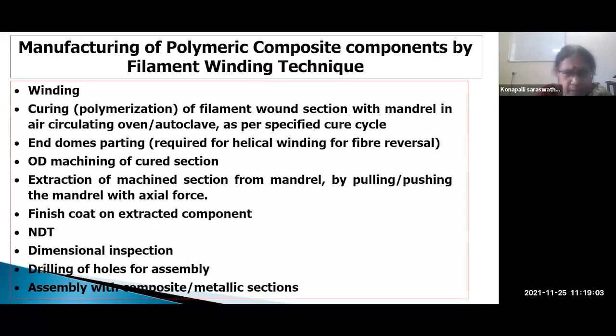These are the various methods. I'm telling in general for any composite; for the filament winding process, I've taken the example. So winding we have to do, either helical, hoop, or a combination of helical and hoop, and then curing. Once we wind, we have to polymerize. So curing of the filament wound section, it is already on the mandrel, so we cannot release the component at that stage. With the mandrel, we have to put it in an oven for heat treatment, rather for curing. Either it is autoclave or oven as per the specified cure cycle.